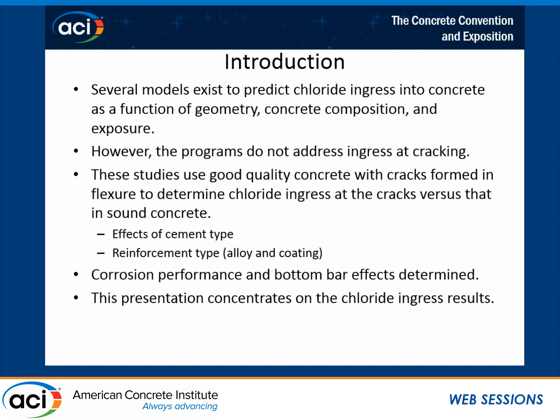Now, why are we interested in this? Several models exist to predict chloride ingress in concrete as a function of geometry, concrete composition, and exposure. However, the programs do not address ingress at cracking, and the famous words are that the concrete really has low ingress of chloride away from the cracks. So the cracking is something we need to know about: what happens at a crack, and how we would modify our models